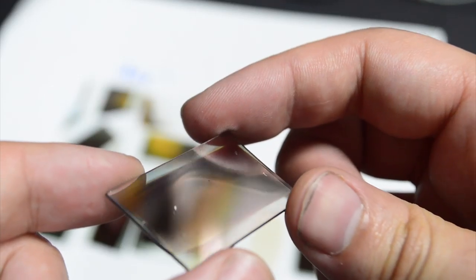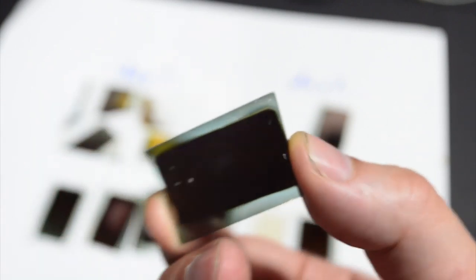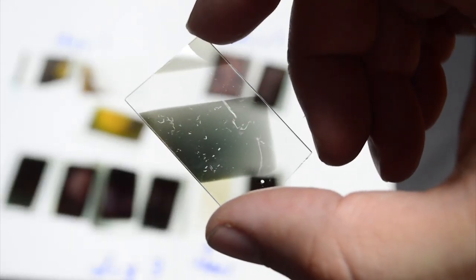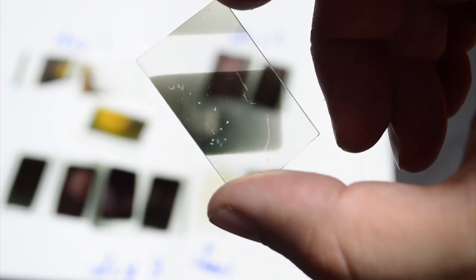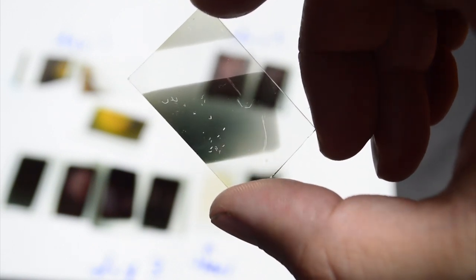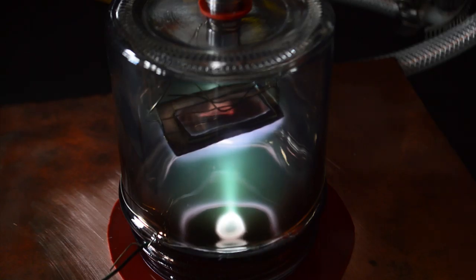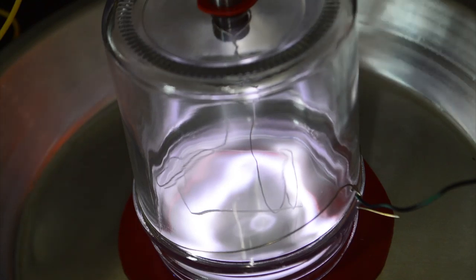But keep in mind that getting things too hot and the carriage itself will start to release metal vapor, which will contaminate your sample. You can see this as a greenish border on some of my samples, or a kind of weird burn spot. It's hard to explain just how excited I was when I got my first thin layer of copper to work. I literally danced around the room for, frankly, an embarrassing amount of time. And on top of it all, I got to see that beautiful glow of copper plasma, which really isn't something you get to see very often. In theory if you do other metals you can get other colors, but most metals just kinda look white for the most part. Sure you could do lithium or strontium to get a red plasma, I just don't know why you would want to do that.